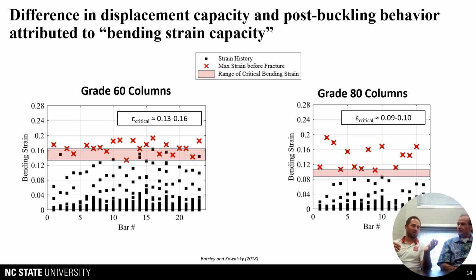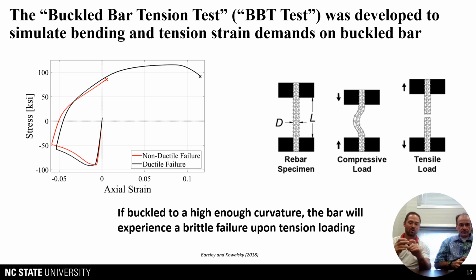And I think at this point, a typical bar that fractures, if you subject it to tension, is going to have necking, and I'm not sure how this is going to actually align. So I tried to take these from way back in the day. You have a bar, I'll just put it against my shirt, right? So you take a bar, it necks, and then it fractures, and there's a very uniform cross section across this. But what we saw, looking back at the pictures of Chad Goodnight's tests and then from our tests, is that the bars that had buckled and then fractured did not experience necking. They basically fractured across the entire cross section. I'm not really sure if that's going to show up that well, but there's no necking at all. And I think there are pictures of this in the actual papers themselves, but the cross section looked much different. So we thought there's some sort of different behavior going on.